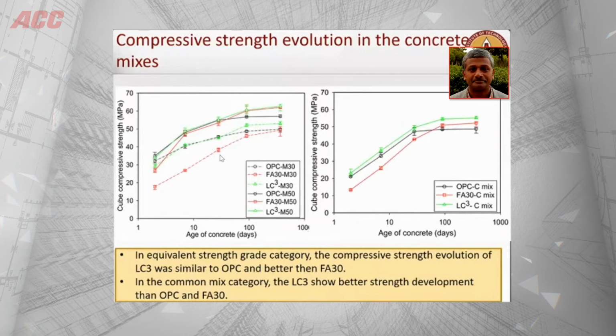Similarly, you see the effects of the M50 concrete. You see that by 1 year, there is not much difference. Essentially all the concretes which were designed for the structural grades ended up getting the right grade. The only thing that was noticeable with LC3 was a higher rate of strength development. Now, at the same level of cement content and water binder ratio, once again there was some difference in the levels of early strength.